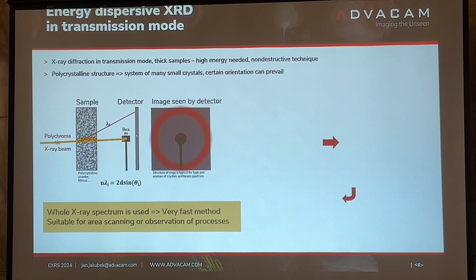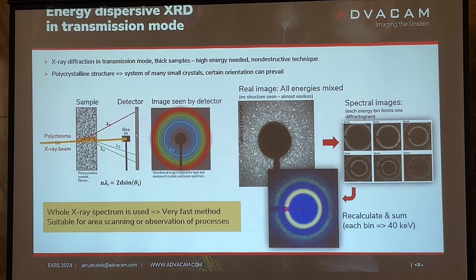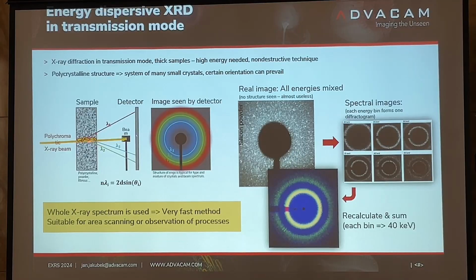What I will show you on top of it is something which was difficult to do before, because this previous method used an energy of 8 kiloelectron volts for measurements. That means that you could analyze only the surfaces of the samples. You couldn't go to the volume. In some cases, if you are welding something, the volume is important, of course, much more than the surface. So to be able to do such a thing, you have to let the beam go through the volume of the sample, but it has to be energetic enough to penetrate it. Then it would be, of course, reflected from some grains, some crystals, and it would create this kind of images we have seen before.